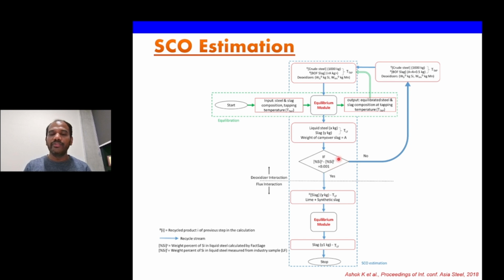Then if the silicon condition is not met, basically we have to go again to the equilibrium model and add the BOF slag, what is given as A, in increments of 0.05 kilogram. So in this way you can increment the small amount of BOF slag every time, so that you get the exact amount of BOF slag. When you add, you are involved in calculating the slag carryover, what exactly has gone, based on the recovery of the silicon that is added as a deoxidizer, right?